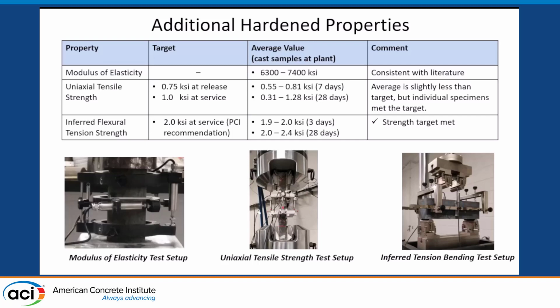We did uniaxial tension strength testing. This is the direct tension setup, which was recommended by FHWA, and I understand there's an AASHTO standard now for this test method. And then we also followed the inferred tension bending test setup, which is essentially looking at tension strength using a flexural bending test and also looking at ductility.